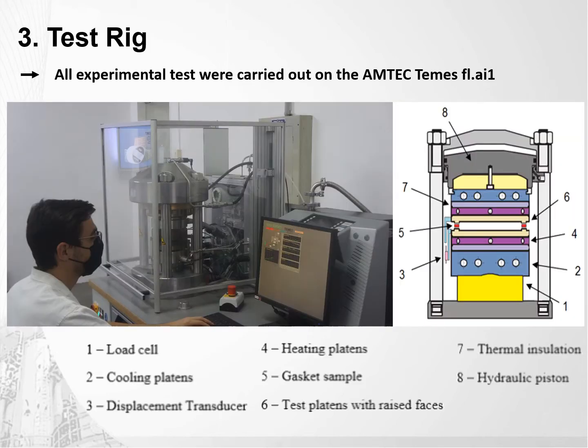All experiments were carried on an instrumented testing machine, which you can see in the picture below. This equipment is a smart press with a hydraulic piston on the top. You can program multiple test procedures and it executes accordingly. It's composed of a load cell to indicate the forces being applied on the gasket, cooling plates, followed by thermal insulation plates to isolate the heating area. The heating platens right here are for high temperature testing. It has three displacement transducers and the flanges and gasket being tested.